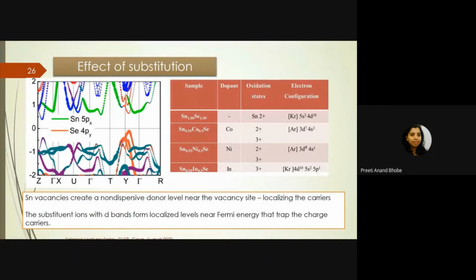Optical spectroscopy tells us that it's a direct band gap. But when you put cobalt or nickel, the d band gets added below the Fermi level. It forms a highly localized peak in the density of states, which is acting as a level to trap the carriers. It is localizing the charge carriers. When the charge carriers try to get excited across the band, there is an additional level because of these dopings that actually traps the charges, and that is giving rise to the lower electrical conductivity in this material.